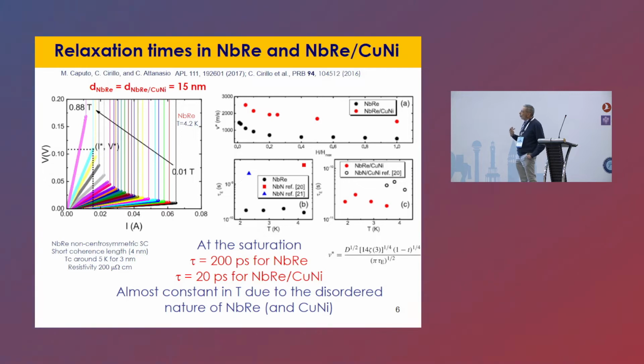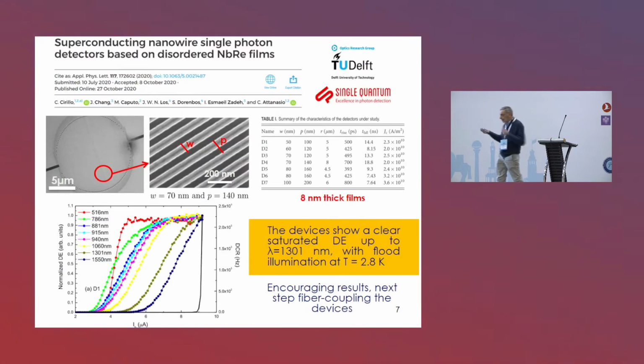The question that we asked ourselves was, what is the critical velocity? What is the inelastic relaxation time associated with this material? And actually, we end up with a quite high critical velocity of 1 kilometer per second, so an inelastic scattering time of the order of 200 picoseconds. So someone in Delft read this paper, and they said, okay, maybe we can try to build real superconducting nanowire single photon detectors.